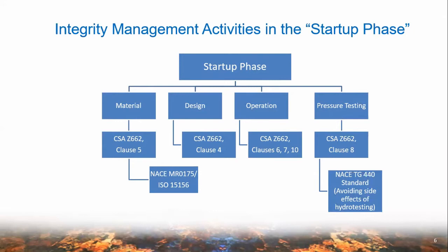It should be further noted that material for sour service must be selected as per NACE MR0175 or ISO 15156. Also, all water used for hydro testing must be removed and the pipeline must be dried before startup. Otherwise, the wear-out phase will appear earlier than you planned due to internal corrosion. NACE is working on a document, TG440, on guidelines to avoid side effects due to hydro testing.